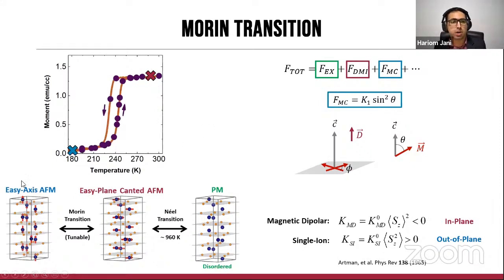So the competition between them as a function of temperature allows us to have very rich transitions at room temperature. This is an easy plane system, which can give the overall macroscopic moment, but at low temperature this becomes an easy axis phase because of the dominance of single ion with respect to magnetic dipolar. And as soon as M becomes parallel to D, of course, the canting vanishes and therefore the signal would also vanish. So this is all very well understood.